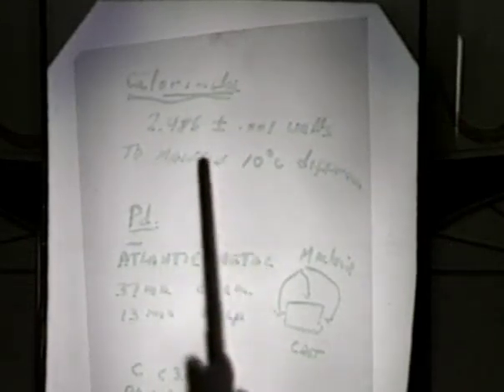So just some numbers on it. The calorimeter required 2.486 plus or minus 1 milliwatt in order to maintain a 10-degree difference between the aluminum can which contained the electrolytic cell and the outside world, which was the thermostatically controlled water, without any electrolytic cell action going on. The palladium itself was obtained from Atlantic Metals, and it was 37 millimeters in diameter, 13 millimeters thick. The cylinder, the thick quarter, was machined on its round edge, and the bottom was left more or less as cast.